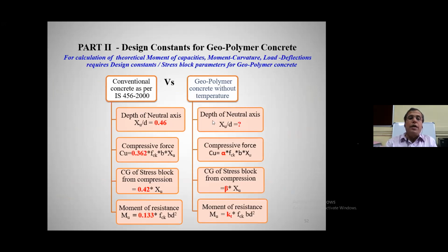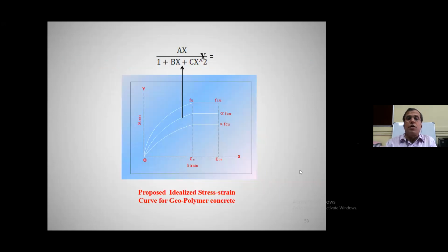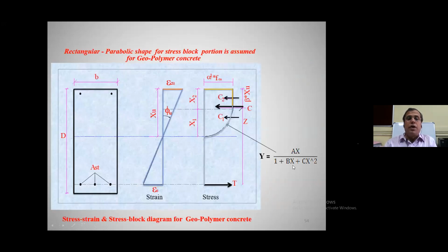Then the point here is that we have conventional values of alpha, beta, gamma, xu by d, or whatever we call stress block parameters: depth of neutral axis, compressive force, then the center of gravity of the stress block from the compression zone, and moment of resistance 0.133 fck bd square. We have these for conventional concrete, and we need them for geopolymer concrete also, for which the investigation has been carried out. As I told you, the equation is idealized, and whatever M20 grade concrete stress-strain curve is there, that stress-strain curve is superimposed onto the RC section.